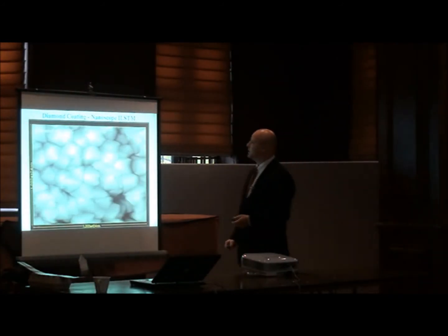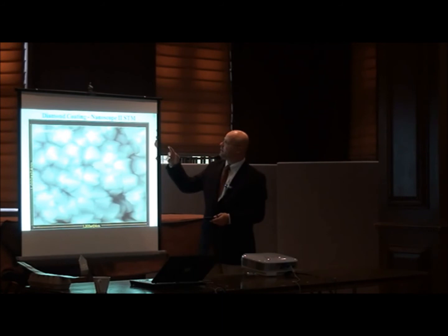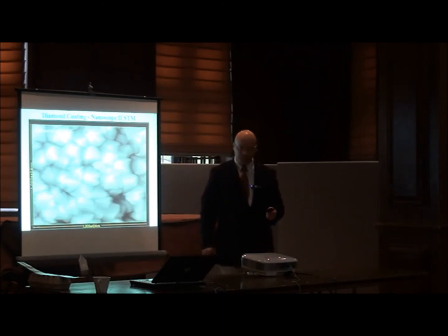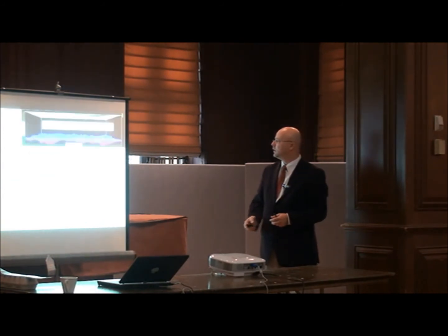If we go back and look at the surface, this is a diamond coating on a silicon substrate, and it was measured with a scanning tunneling microscope. As you get on the diamonds sitting on top of the diamonds, we're in this region of growing area on the surface, as the tiles get smaller and smaller. When we get to this section here, our tiles are actually sitting on the facets of the diamonds. So we're not getting as much additional area as we go there because those facets are smooth. So at a very fine scale, if you were only looking at one facet, the diamond's not very rough.